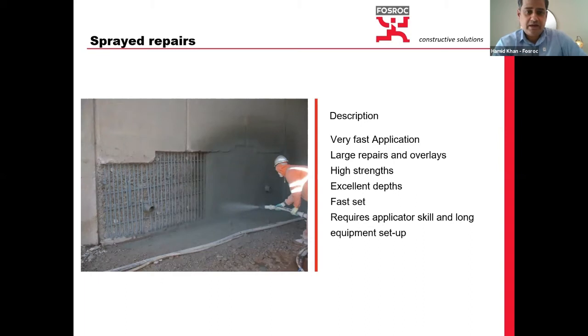Similarly, after hand application, there are sprayed-on systems as well. Sprayed-on systems are very fast in application, but this is also an important part in the selection for a durable repair: if you have larger areas and access to these structures where you can bring your machine in, spray is really good. However, we have seen that form and pour also works very well if you have access from the top and bottom: formwork underneath, and you can pour if it's a slab. In such situations, sometimes you can do letterbox formwork and apply or pump as well. So there are different techniques, and it depends totally on the site allowance and whether the site allows us to take such equipment.